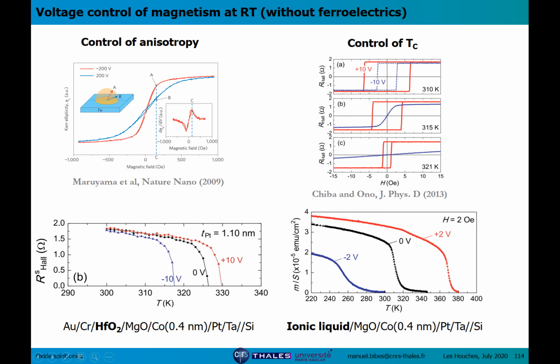layer. This is from Teruo Ono from Kyoto, and he has done a number of very nice experiments controlling magnetism of very thin layers of cobalt, 0.4 nanometers, very, very thin. And either applying a voltage across a dielectric, in this case they had MgO and hafnium oxide, or using ionic liquid, which of course allows to accumulate and deplete a much larger amount of charge. You can see here that they were able to control the shape of the magnetic hysteresis loop, basically turning on and off magnetism at a given temperature.